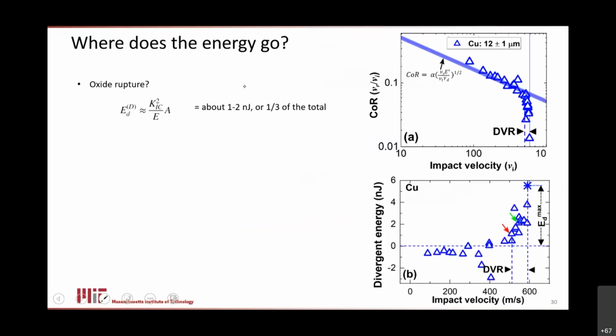Now, if you do a little back of the envelope math, actually that turns out to be a really interesting number, because if you know the area that you've delaminated and you know the fracture toughness that prevails at that interface, again, it's on the order of 1 megapascal root meter, that lets you calculate the amount of energy that you spend on rupturing oxide. And what we're finding is that it's something on the order of 1 or 2 nanojoules. So in the case of copper, when we are damping and slowing down that particle, about 1/3 of the total energy getting pulled out is being spent on breaking up that oxide layer. So oxide rupture and breaking is a big part of the work that goes on in order to produce metallurgical bonding. What's the rest of that energy?